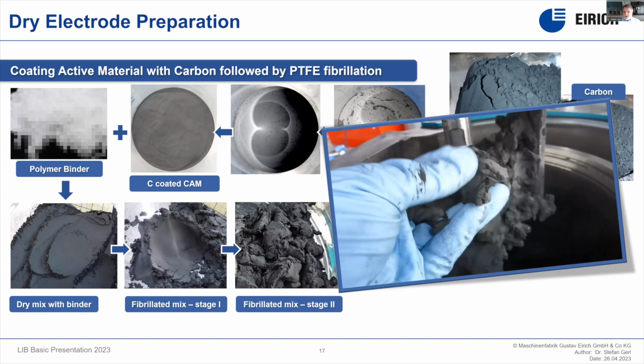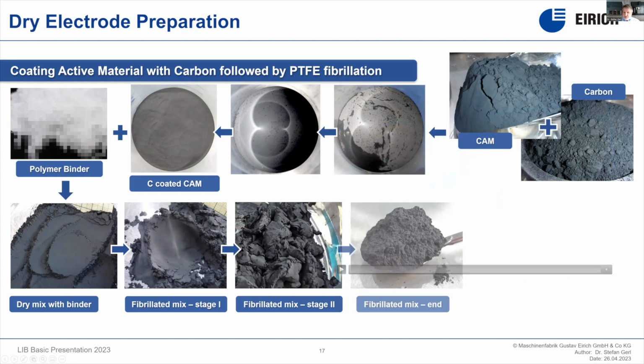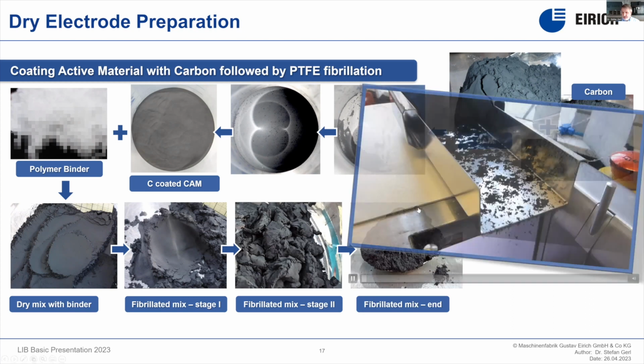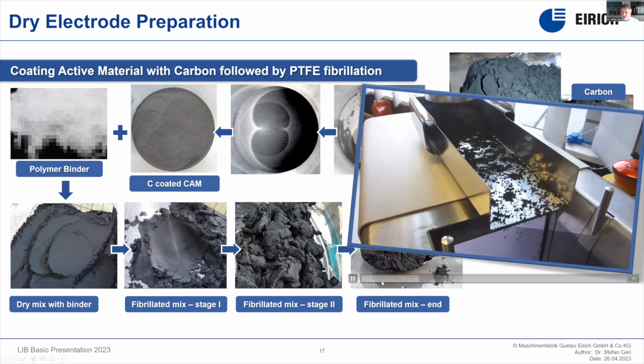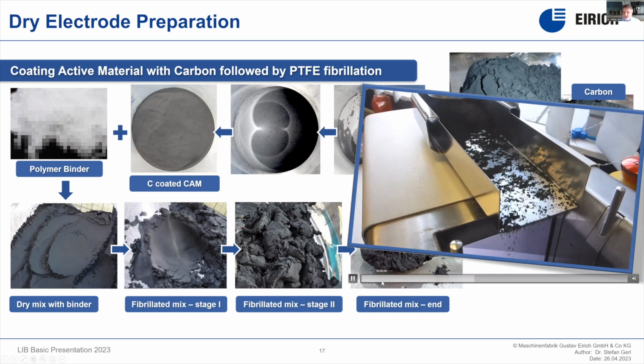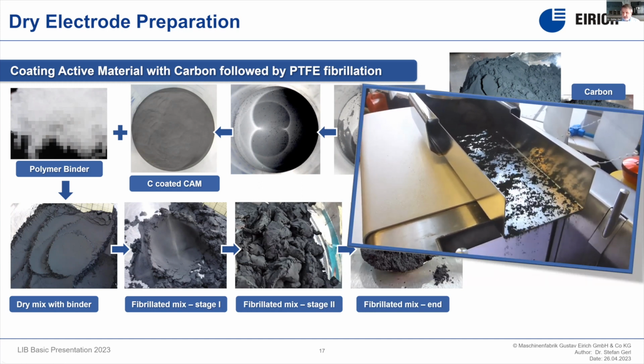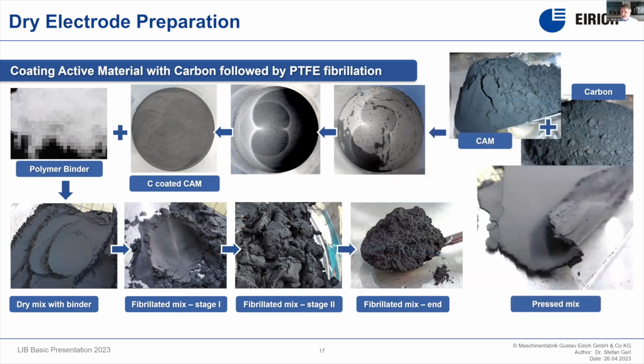And this is where we are now starting to, let's say, form a material which can be conveyed. We are cooling the material, we are chopping the material inside of the machine, so that at the end we have a structured mix which is incorporating fibrillated material, coated material, and which can be quite easily dosed and homogeneously distributed, for example, into a calender system. Out of this, then you have, of course, a fibrillated or a film forming mechanism where you have a complete dry mix.